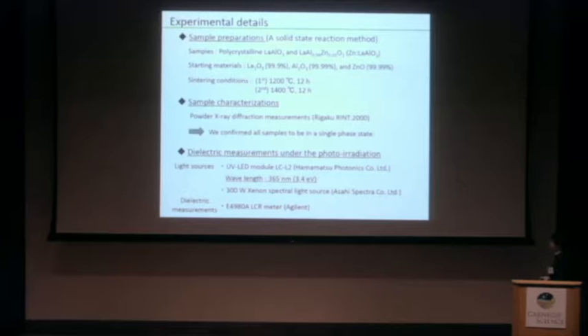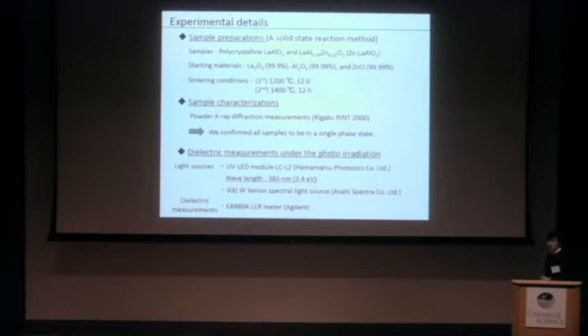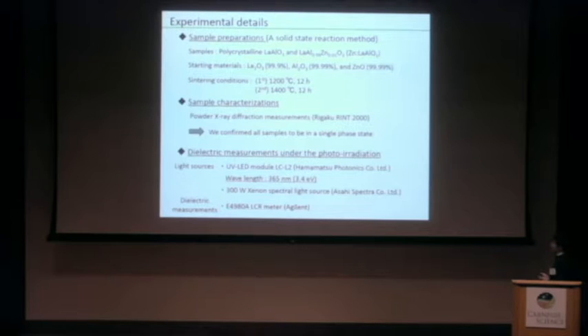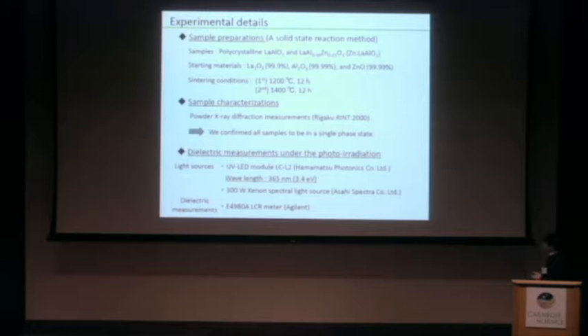This slide shows the experimental procedure. We synthesized polycrystalline samples by a solid-state reaction method and confirmed all samples to be in a single-phase state. Then the dielectric permittivity is measured under photo-irradiation. The light sources used are LED and xenon spectral light sources.